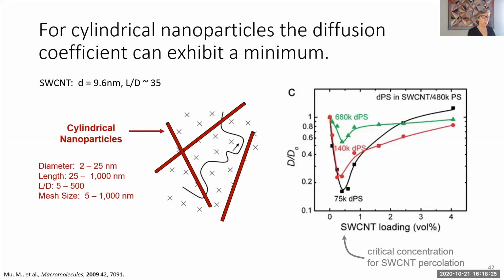Okay. So the very first diffusion experiments we did were with carbon nanotubes, thinking about how the carbon nanotubes would disrupt or not the entanglements and how that might impact the diffusion coefficient. And we had this very unusual result. As we added more nanotubes, we first saw a dramatic drop in the diffusion coefficient. With half a volume percent of nanotube, the diffusion coefficient is dropping by 80% for the smallest molecular weight, and it's not as dramatic for the highest molecular weight. So we have this dramatic drop in the diffusion coefficient, then afterward it recovers.